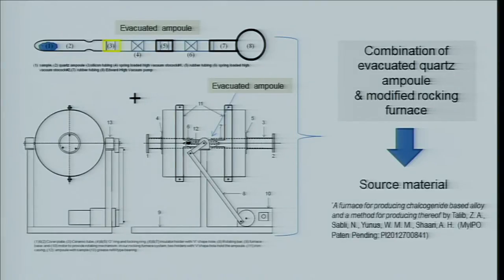And in this case, we would like to give energy to the compound or to the mixture of powder. But we would like to do it free of impurities. The environment has to be free of impurities, and what better environment than a vacuum. So to do that, we put the mixture of the powder in what we call ampules. But the thing is, if you have a very small powder, it just sucks the powder out of the ampule. So Dr. Nordin improvised by using what we call a double valve system, with which we have managed to produce high vacuum in the ampule.